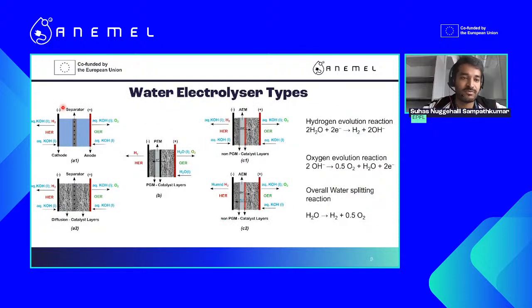These historically come in different configurations. One of the oldest electrolyzer devices are the classical alkaline electrolyzers, which use aqueous potassium hydroxide, high concentration salts, with a small gap between them and a separator, which basically separates the gases that are evolving in the two chambers. So we send in water here in these two chambers, and then you apply electricity, preferably from renewable sources. And then you have the electrocatalyst, which are at this junction here, performing the water splitting reaction, producing hydrogen and oxygen. Similarly, this old, I think it's more than 100-year-old technology was advanced further to eliminate this gap for various reasons. And then you have this zero gap configuration. Again, the electrocatalyst layer is now slightly closer to the membrane, and then you have similar reactions happening.